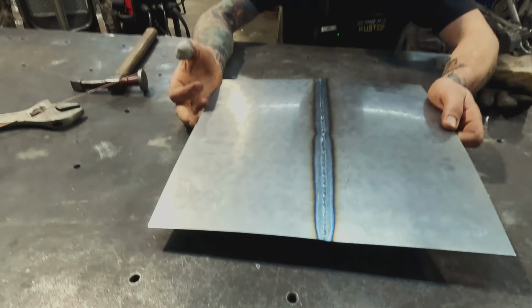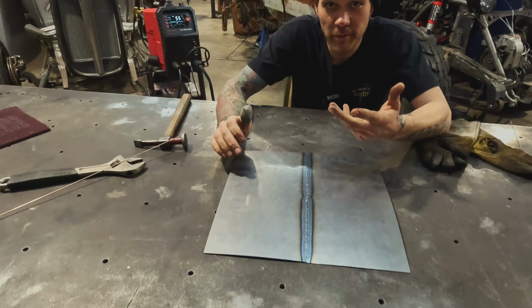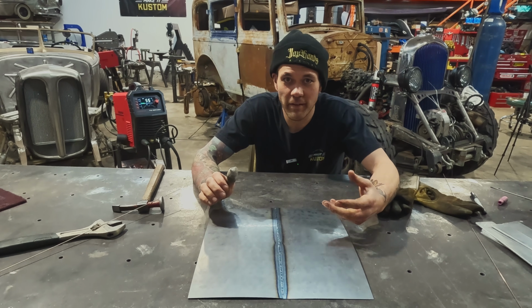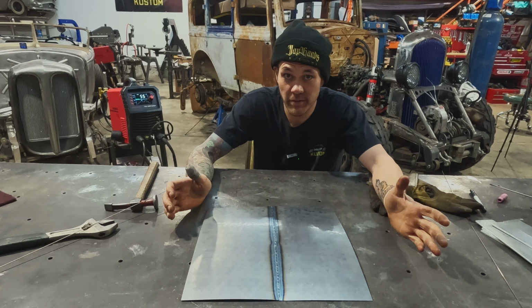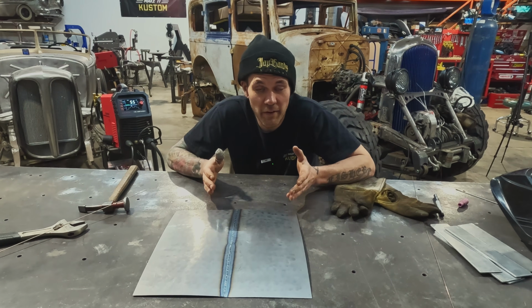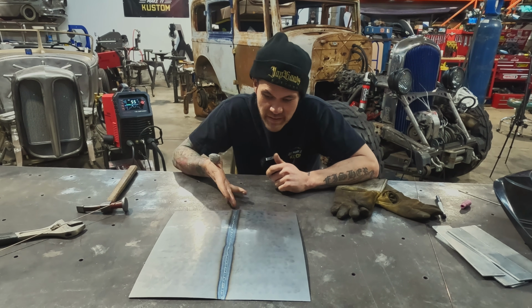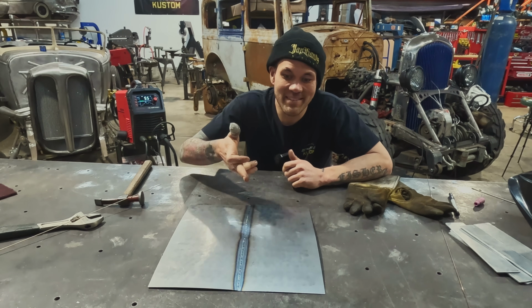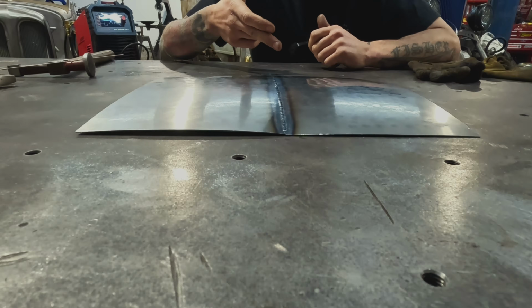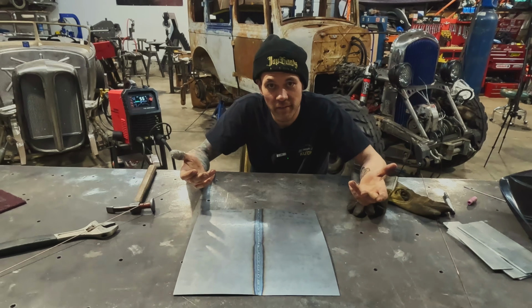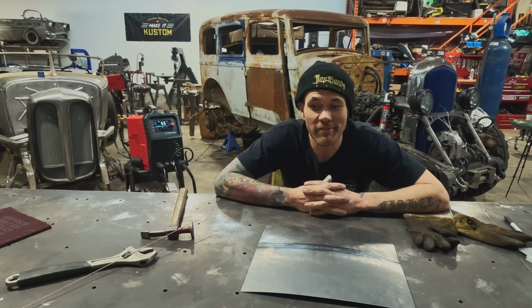I'm very happy with the weld itself. This little spot where you see my heat change, that's the stop start. No matter what you do, this is warping it. You can't ask me, how do I do it without warping? Because it doesn't happen. We would have to hammer this out. But because it's such an even and consistent weld and consistent heat, it shouldn't be that hard to planish that out. There you have it.